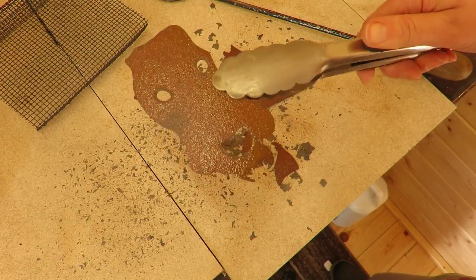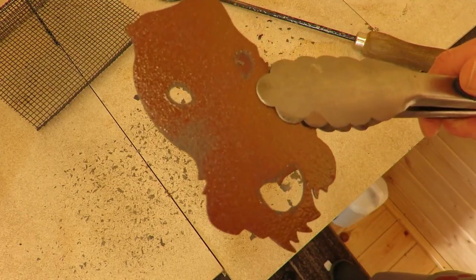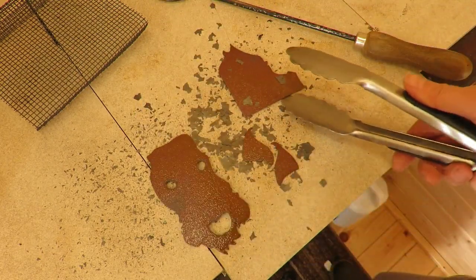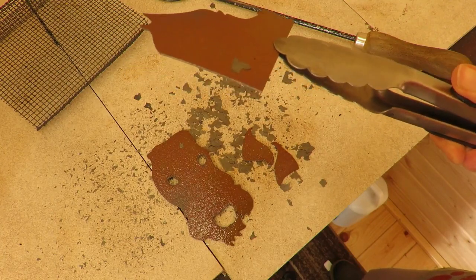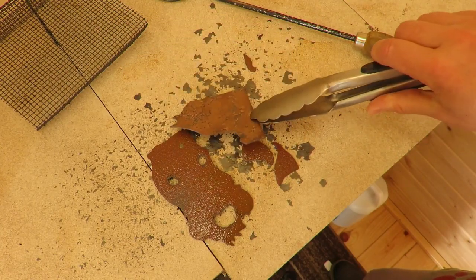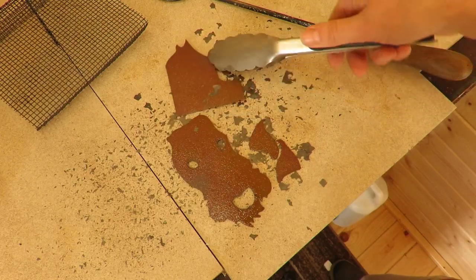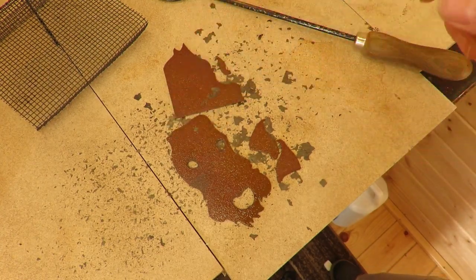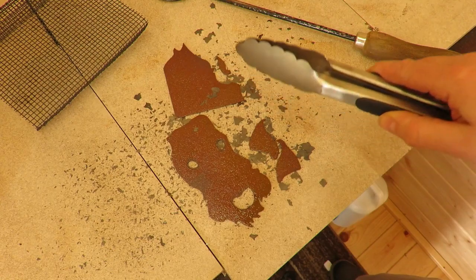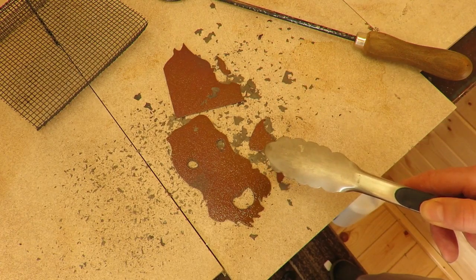As far as the color goes, it's quite dark, but that's okay. I missed out — you can see his cheek is a little bit blackish, but that's okay; I kind of noticed that when I was putting it into the kiln but thought to hell with it. You can see because there isn't any enamel on the back, it's gone slightly warped. That'll be flattened out, and even if you hear cracking, that's fine — once it goes back into the kiln, all of that glass will fuse together again. So I'm going to do the liquid enamel on the back, let it dry, do a second coat of the same color, and then review the situation.